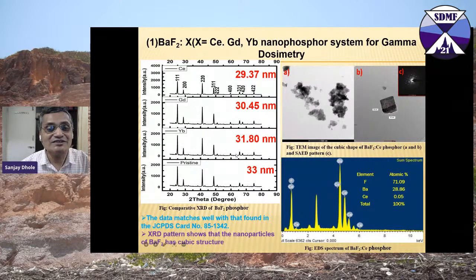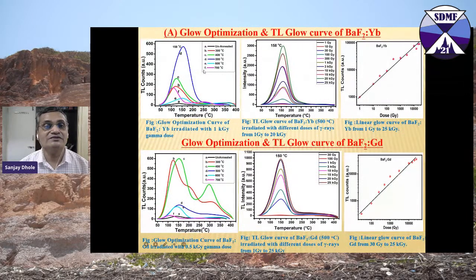So this is the structure, and this XRD pattern shows that the nanoparticle has a cubic structure. This is the morphology, and this is the EDS pattern, which shows the elemental analysis, from where you can confirm that there is fluorine, barium, and cerium, and then the percentages accordingly. This is the glow optimization curve.